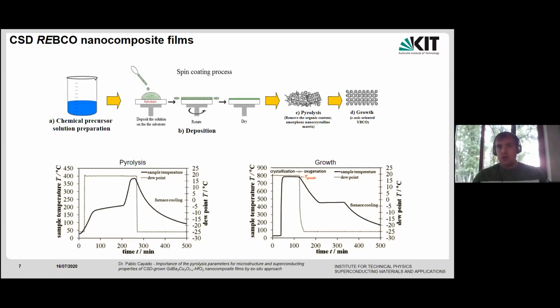REBCO phase. This growth, as you can see here below, has two steps. First is the crystallization to achieve the phase, and second is the oxygenation to get the orthorhombic phase. Because, as you know, after crystallization we have the tetragonal phase, so we need the oxygen to convert it into orthorhombic. And this is the pyrolysis that we are doing. So pyrolysis is a low temperature step, only up to 400 degrees, which is, as I said, for removing organic content.